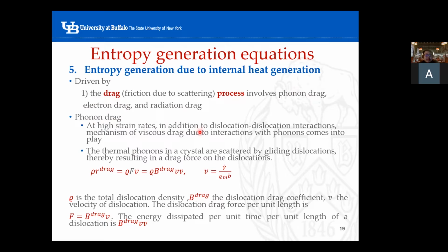Basically, at a high strain rate, in addition to the dislocation-to-dislocation interactions, we also have these mechanisms resulting in a viscous drag. This viscous drag is due to the interaction with phonons and the dislocations. These thermal phonons in a crystal are scattered by these sliding dislocations. When there's a dislocation movement, the phonons basically provide an impedance force, and that results in a drag force, leading to energy dissipation.